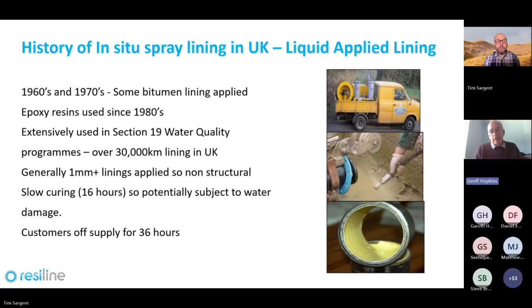The additional issue was that if you put cement mortar linings inside old small bore pipes, you tended to reduce the bore even further, and pipes that were sized for Victorian household water demand couldn't carry enough water for modern households with washing machines, dishwashers, everything else. So again, a reason why the industry was looking for thin film coatings.